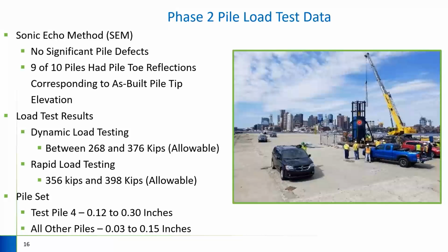So for the phase 2 pile load testing, similar to phase 1, we performed the sonic echo method testing across all of the piles. One good thing to note was that we were able to see that 9 out of the 10 test piles had toe reflections within plus or minus 2 to 3 feet of the as-built pile tip location plan. So it shows you that the records from the previous data were actually fairly accurate. In addition, we did not see any significant pile defects associated with these piles.